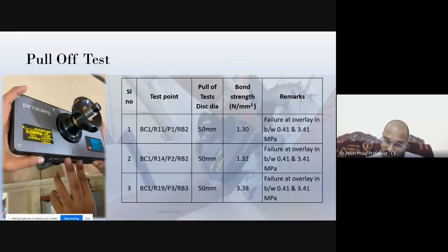Lower than 0.41 means the rebar is already corroded. There is no bonding between the reinforcement and the cover concrete. So we can conclude based on that. If you look at the 3.38 and 1.32 values, we can say that some concrete has the quality of M30 and some is lower, maybe M20 or less. Where 1.3 is coming, it is maybe around the M15 range only. So this kind of thing we can identify from the bond strength value.